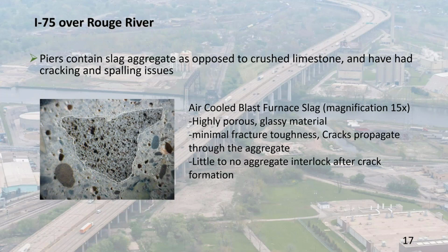This material has minimal fracture toughness, and cracks go right through the aggregate, unlike standard aggregates where they bridge cracks, and cracks have to expend energy to work around. They'll just plow right through the slag aggregate, which means you have essentially no crack resistance and no aggregate interlock after the crack formation.